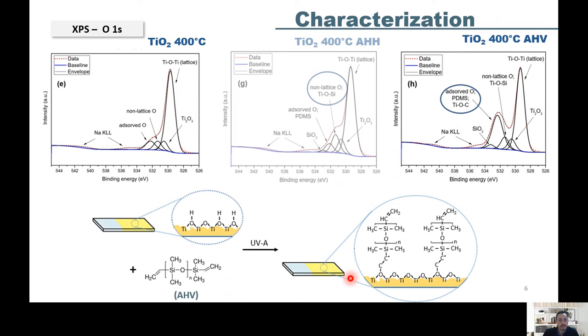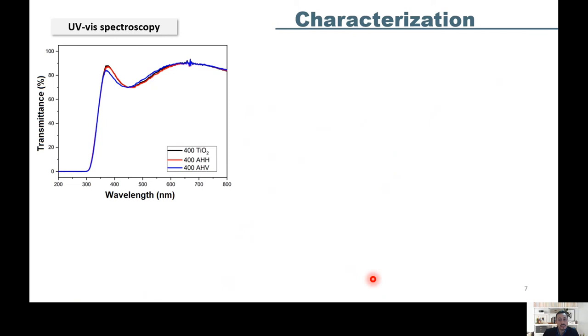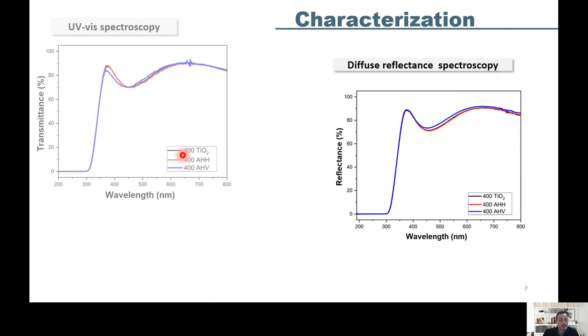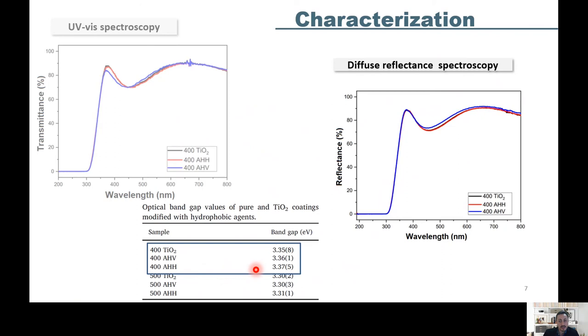The spectra in the ultraviolet-visible region show that there is practically no difference in light transmission through thin films. Even after modification with polymers, the diffuse reflectance spectroscopy reveals the optical bandgap values of the samples and shows that there is practically no variation in these values. In this table, we can see the bandgap values of samples treated first at 400 degrees Celsius and 500 degrees Celsius.